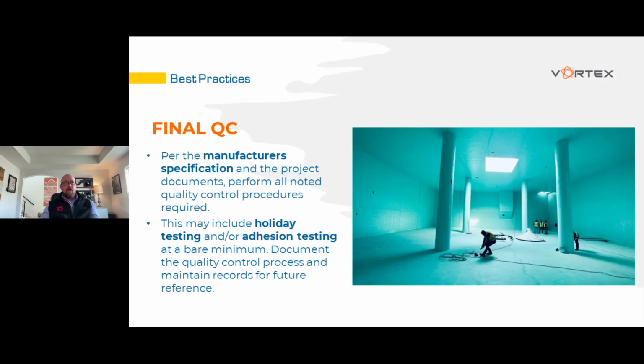And then finally, that final QC. Once the material has been installed properly, there's a manufacturer-specified QC protocol to follow to make sure that the material itself is monolithic, and that there are no holidays or pinholes in the material itself. If there are anomalies in the material through installation error, then we need to address those and get them fixed before we put something into service. And those are the things that we look at at a bare minimum.